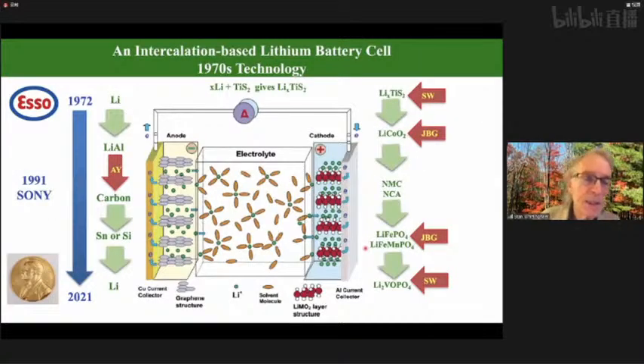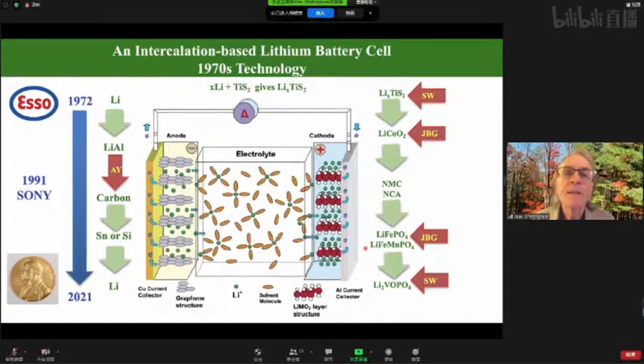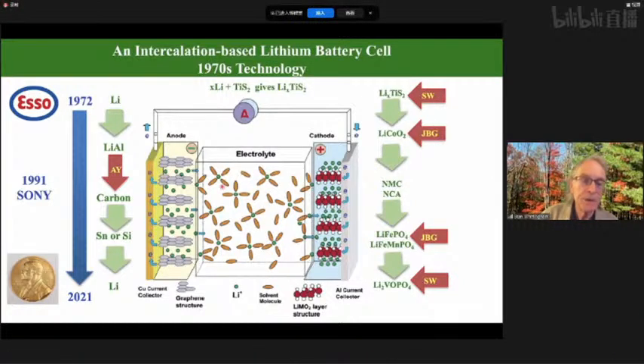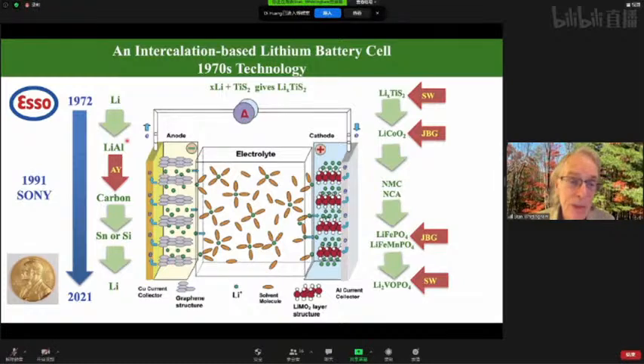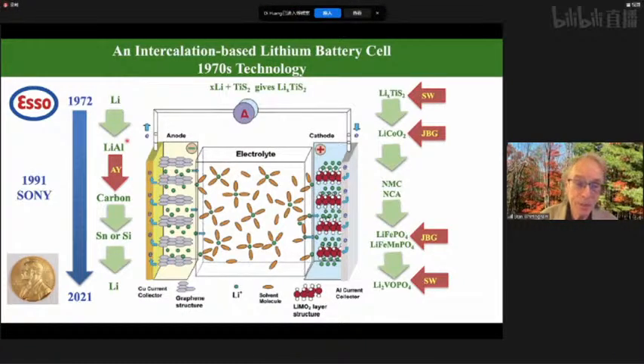So let's look at the history of lithium-ion batteries over this last 50 years. So we start out in 1972. Exxon was then Esso. Some of you may be old enough to remember that. We start out with a lithium anode. We very quickly learned that you've got dendrites, so we switched to lithium aluminum. That only cycles maybe 100 times. It's a very brittle compound, so it tends to crumble up.